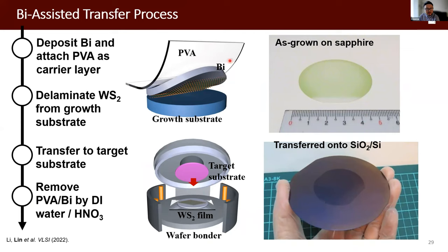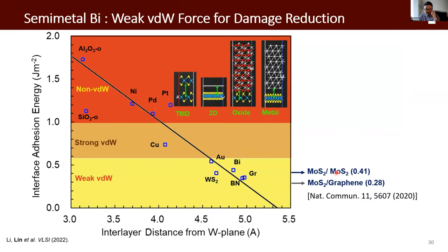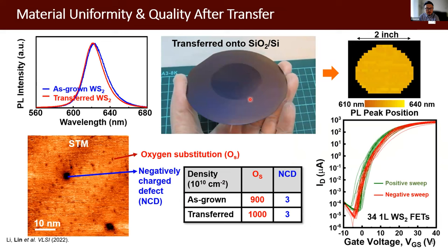And we have tried different metal materials as the interfacial layer, and we found that bismuth gave us the best transfer results. That is also because of the weak interaction between bismuth and 2D semiconductors. So this is a DFT calculation for different metals and the 2D semiconductors, and the interfacial adhesion energy characterizes how strong the interface interaction is. And bismuth is very close to all the other van der Waals interaction materials. And this basically gives rise to the sweet spot for the transfer. So the adhesion is strong enough to hold all the 2D materials, but weak enough to not introduce any damage. And with that, we demonstrated a wafer scale transfer approach.